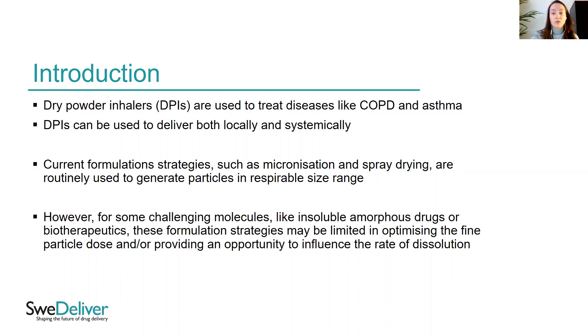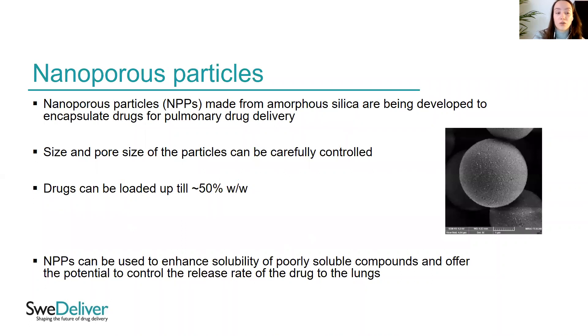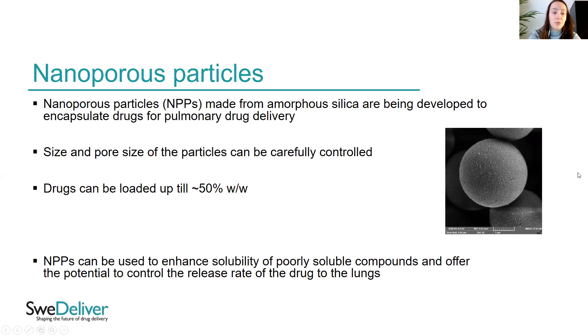Therefore I would like to introduce you to nanoporous particles. Nanoporous particles, NPPs, made from amorphous silica, are being developed to encapsulate drugs for pulmonary drug delivery. You can see one of the particles here — they are very nicely spherical. The size and the pore size of the particles can be carefully controlled, drugs can be loaded up to 50%, and NPPs can be used to enhance the solubility of poorly soluble compounds and offer the potential to control the release rate of drugs to the lung.